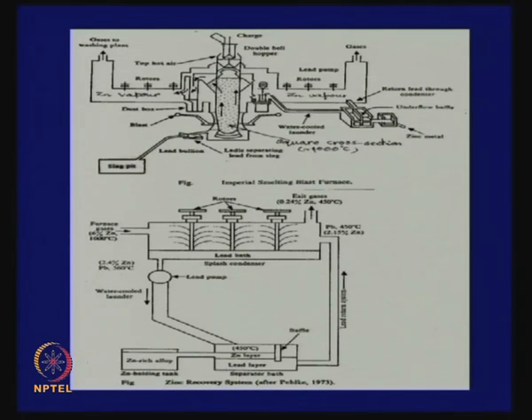I have also mentioned that in this case the furnace is of square cross section, and operates at about 1000 degrees, more or less similar to the lead blast furnace operation, which operates at 1200 degrees. I did mention why it is called the imperial smelting furnace. You should guess the very word imperial should tell us that it was developed in England. So, it has come from United Kingdom, that is why they have named it imperial smelting.